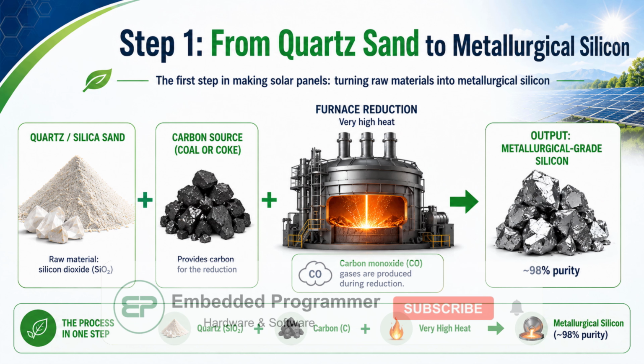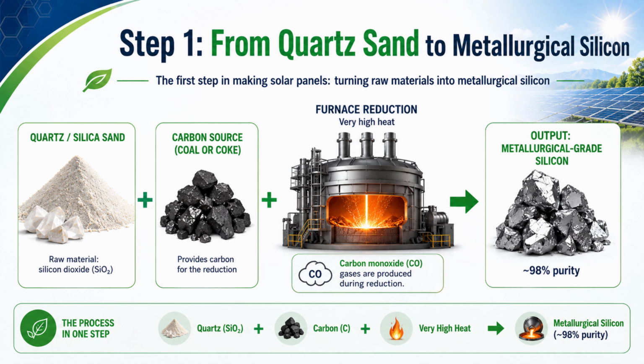The manufacturing process starts with quartz or silica sand. Chemically, this raw material is mostly silicon dioxide, written as SiO2. Silicon dioxide is very common in nature, but it is not directly usable as a solar cell material. To extract silicon, quartz is mixed with a carbon source such as coal, coke, or another carbon-rich material. This mixture is heated inside an electric arc furnace at extremely high temperatures. Inside the furnace, carbon reacts with oxygen from the silicon dioxide. This reduction process separates silicon from oxygen. The result is metallurgical grade silicon.